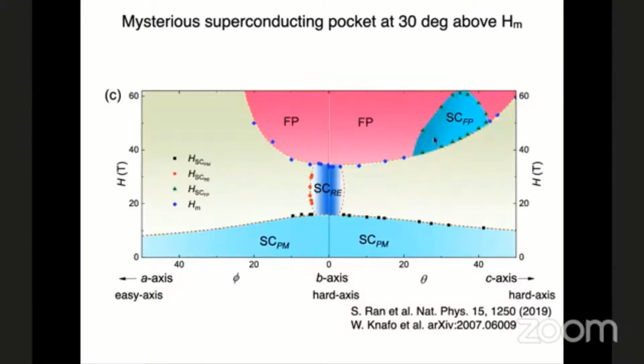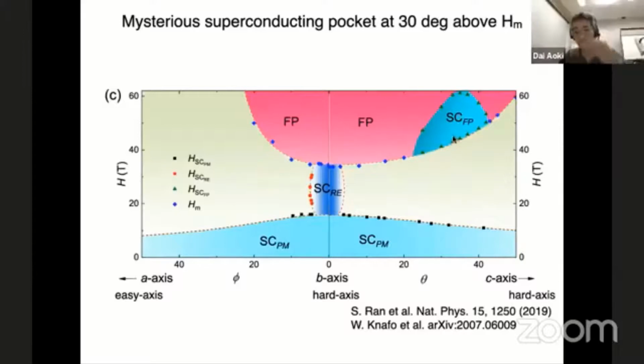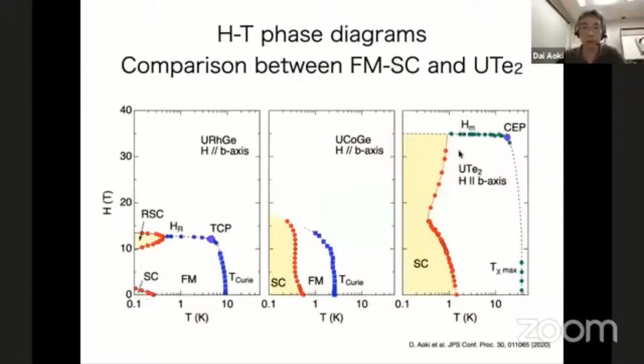It shows superconductivity in the polarized phase. And this reentrant superconductivity is also confirmed by William Knafo in Toulouse. So this is real. Of course, the measurement was done by the resistivity curve, so we should confirm by bulk measurements, but at least in the resistivity this is confirmed. This is really mysterious.